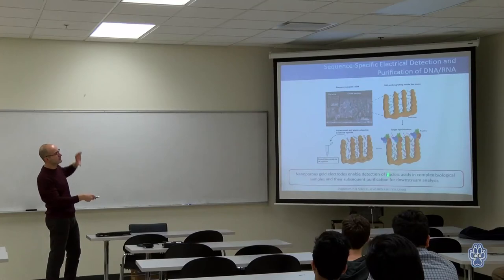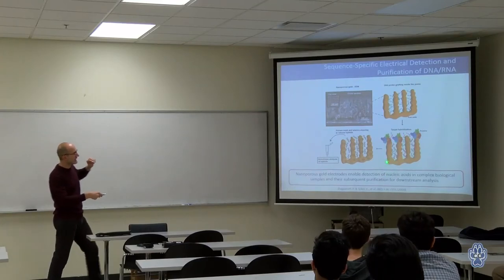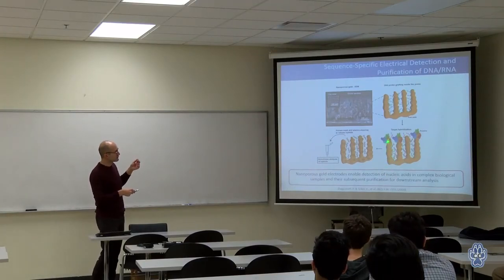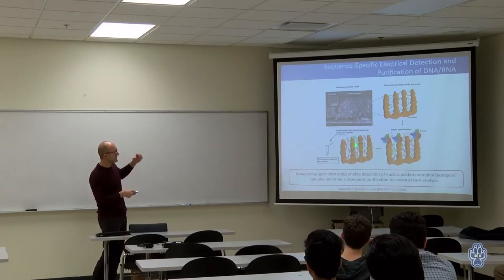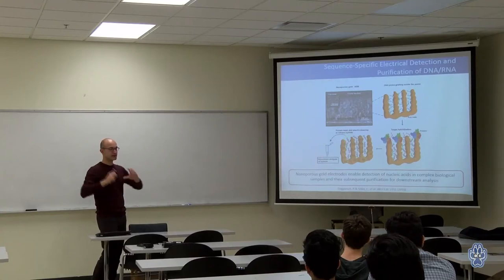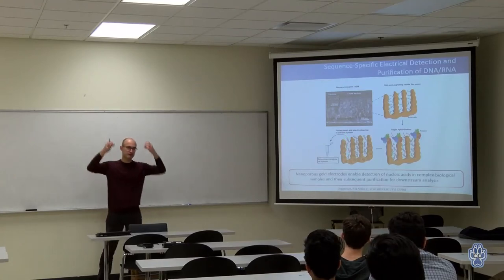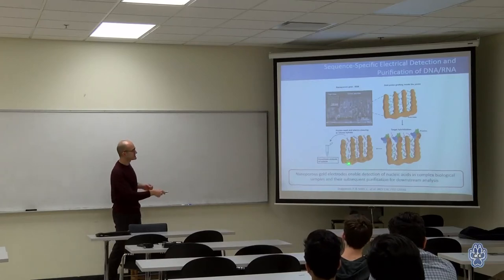So this is kind of a schematic of a pore cross-section. And now we can apply an electrochemical potential to break the sulfur-gold bond. So now the DNA molecules that we've captured are in that porous sponge. And if we apply a negative potential, DNA has these phosphate groups which are negatively charged, you can actually push the DNA hybrids out of the solution.